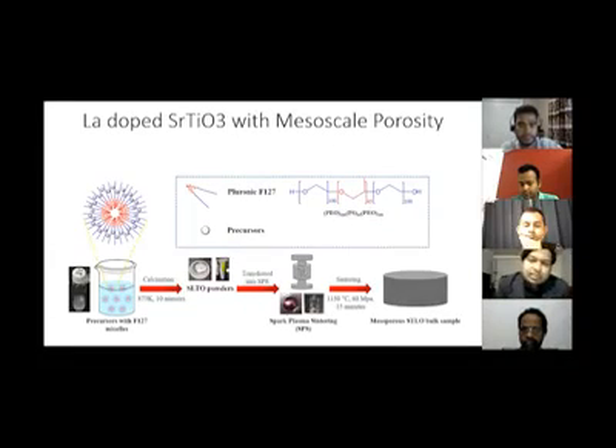To improve the electrical conductivity, we dope with lanthanum. But our main target is to reduce its lattice thermal conductivity or phonon thermal conductivity. So we try to introduce some mesoscale porosity, around 2 to 5 nanometers, in our bulk sample so that it can scatter the phonons. If we can scatter the phonons, then we can reduce the lattice thermal conductivity. That is our main job.